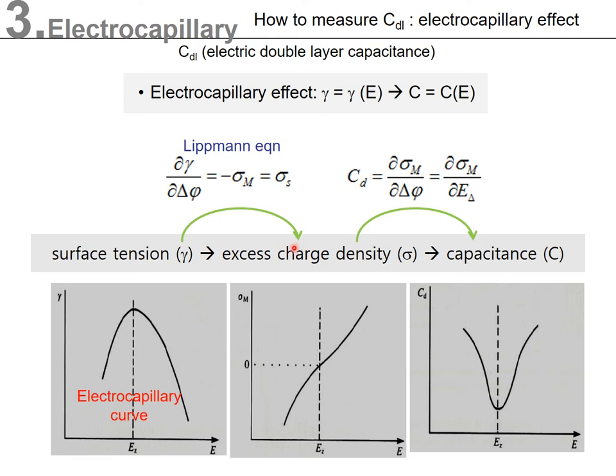So let me think about the curves. The starting point was surface tension. So this is the electrocapillary curve, surface tension versus potential. At the point of zero charge, you would have the maximum surface tension. However, when you go to a potential far from the point of zero charge, in the positive or negative direction, the gamma goes down on both sides. After the Lippmann equation conversion, this curve becomes the excess charge density versus potential curve. Of course, you could also get this graph by taking slopes of the first electrocapillary curve. And then one more conversion. Finally, we could obtain the capacitance.